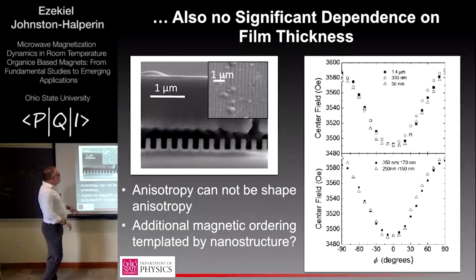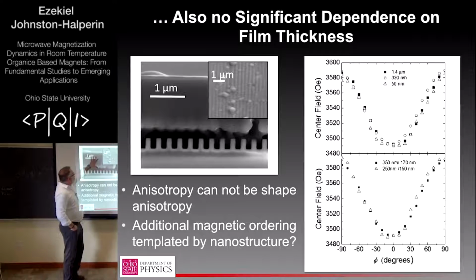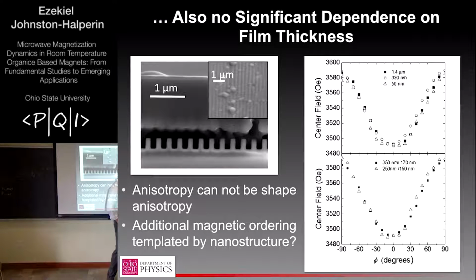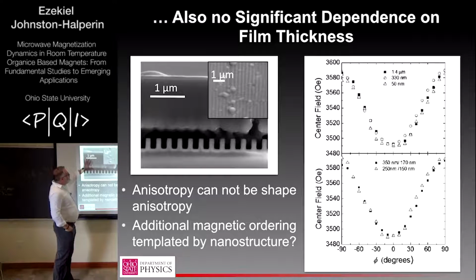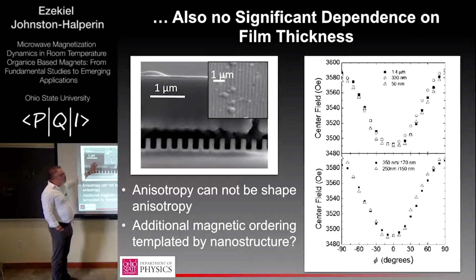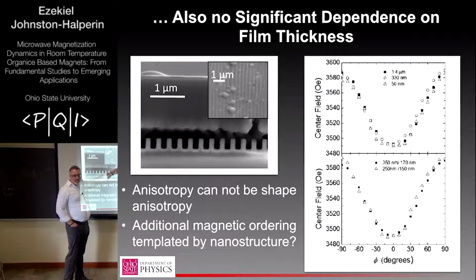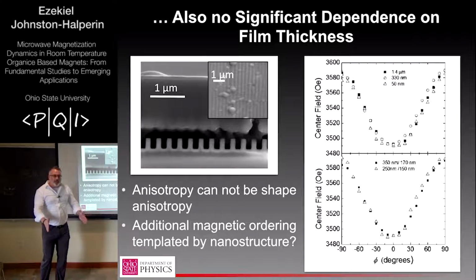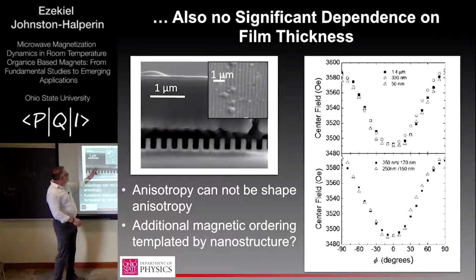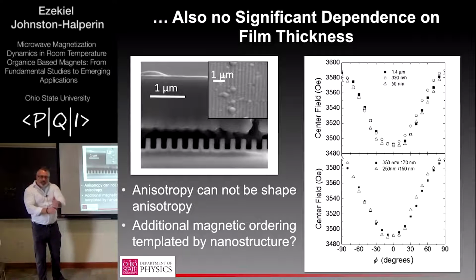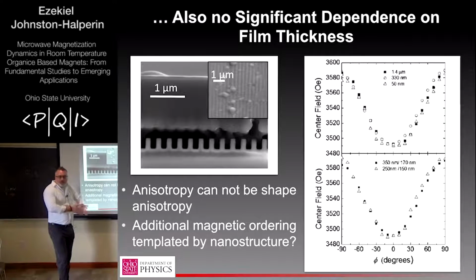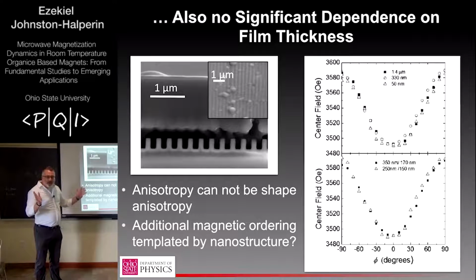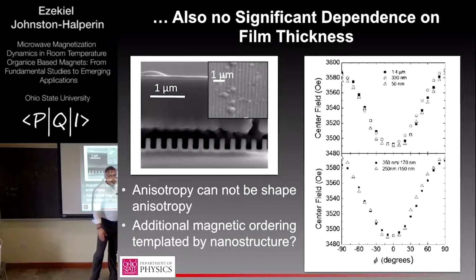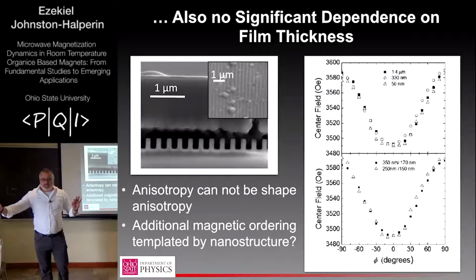As you can see, this is probably the most dramatic case. This is a 1.4 micron film, the black dots here. So the film's completely recoalesced. If I was going to do a magnetostatic modeling of this, it would look like a thin film. From the top, you can still see ridges. So there's some sort of memory in the material of the fact that it started off as individual wires. If you look carefully, you can see sort of faint vertical striations here. So there's some sort of interface that persists even after it recoalesces. But as far as dipole fields are concerned, that doesn't matter. But the anisotropy is exactly the same as for well-isolated nanowires.